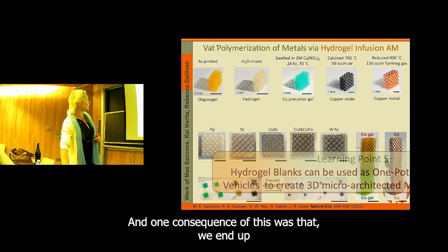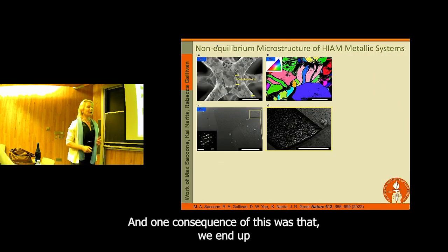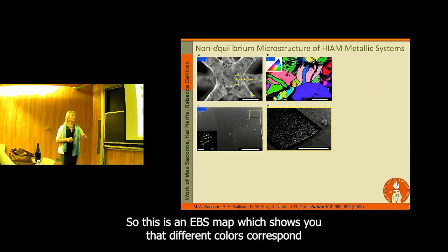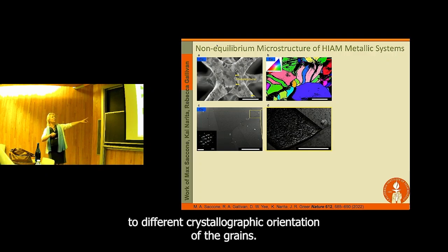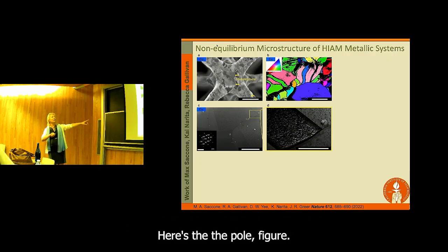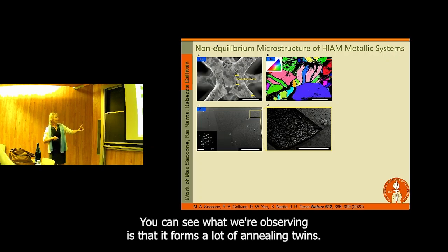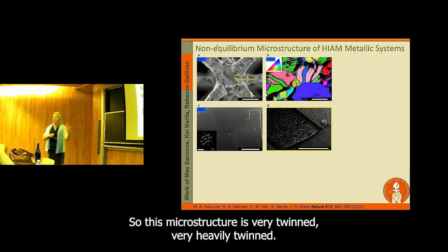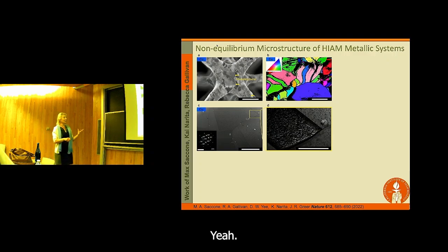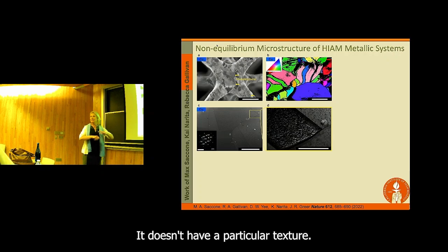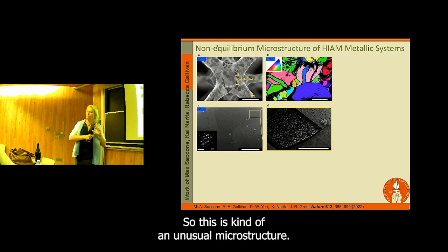And one consequence of this was that we end up with some very weird microstructures. So this is an EBSD map, which shows you the different colors correspond to different crystallographic orientation of the grains. Here's the pole figure. So this is copper. What we're observing is that it forms a lot of annealing twins. So this microstructure is very twinned, very heavily twinned. It's polycrystalline. It doesn't have a particular texture. So this is kind of an unusual microstructure.